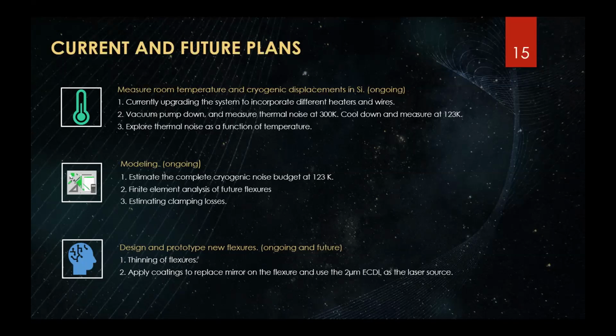Ideally we want to etch a small membrane in our entire flexure, which is 100 micron thick, so that the thermal noise is dominated in that small membrane, and also apply coatings to replace the mirror on the flexure, and ultimately try and use a 2 micron laser source to make these measurements.